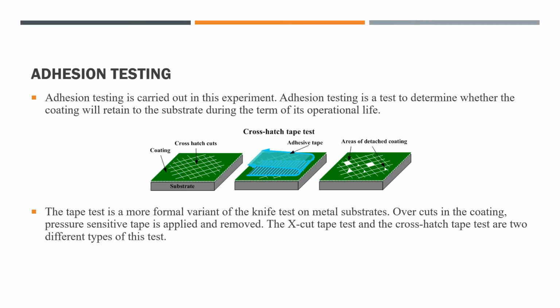The cross-hatch tape test is designed for use in the lab on coatings that are less than 5 mils thick. Instead of an X pattern, it uses a cross-hatch design. To ensure that the incisions are properly spaced and parallel, use a cutting guide or a dedicated cross-hatch cutter with various preset blades. The cut area is next inspected and assessed once the tape has been applied and removed.